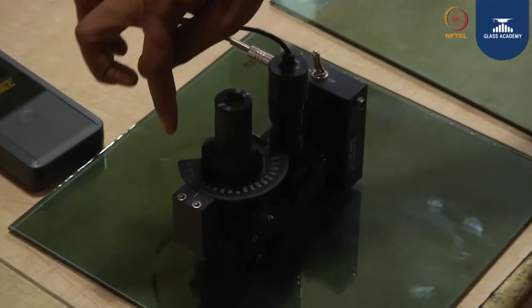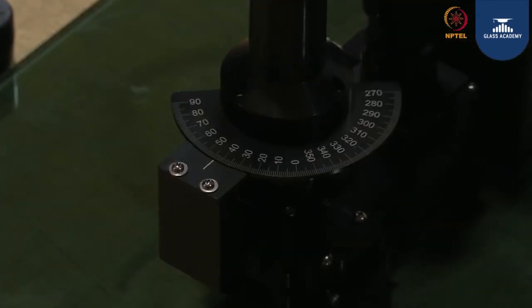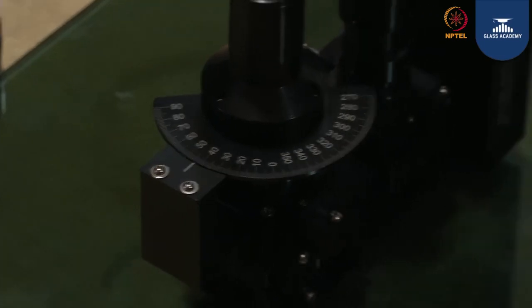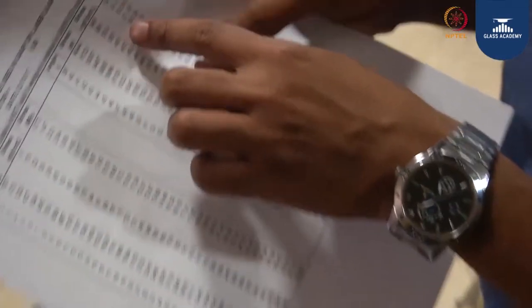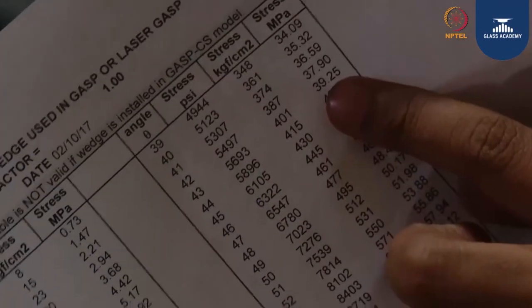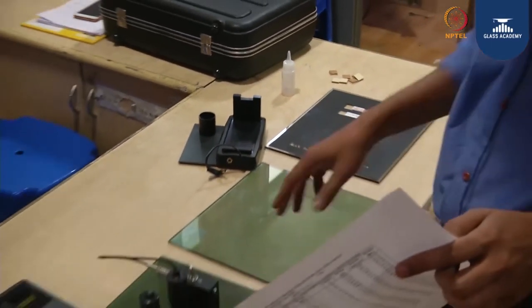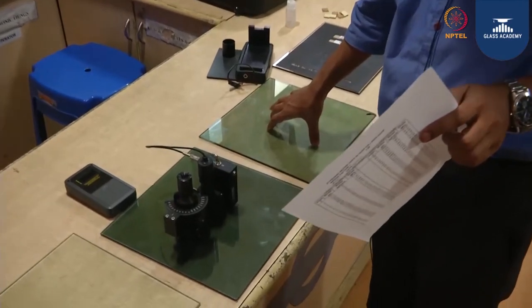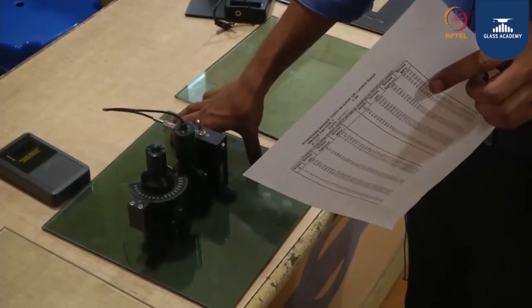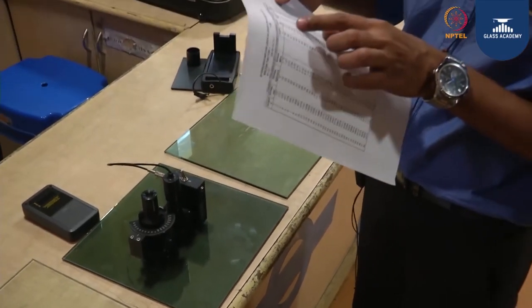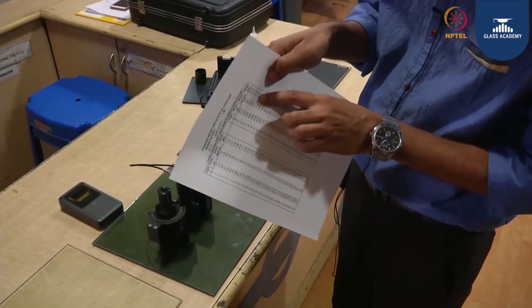You see here, now the reading it is showing is 43, and 43 with respect to MPa is 39.25. So earlier we have seen for the annealed glass it was 14.49 MPa. The same thing when I am checking on the heat strengthened glass, it is coming to be 39.25 MPa.